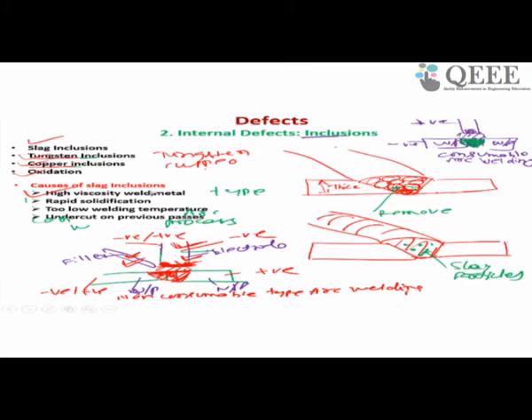It may also happen because of rapid solidification. Our objective is that the slag should float on the top, but if solidification happens in the weld pool before the slag floats up, the slag will be entrapped inside the weld pool. As a result, you will get slag intrusion. So rapid solidification is another important parameter which entraps the slag.